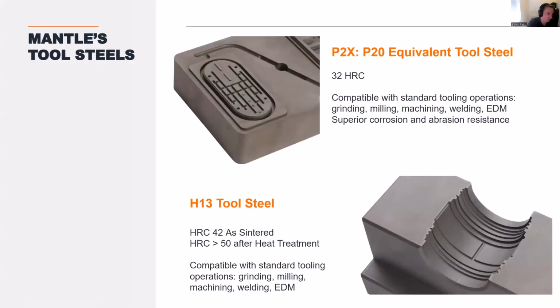Today we have two tool steels available. A P20 material, which we actually call P2X. It's very, very similar to a P20 material. It actually has superior corrosion resistance that comes out of our process with a 32 HRC. And then we have an H13 tool steel, which is actually our more popular material. Comes out of the furnace at a 42 HRC and can be heat treated all the way up into the 50s. Both of these, I should note, are fully compatible with traditional finishing, because we like to say our process gets you anywhere from 50 to 75 to 95% of the way there. Generally, tools need a little bit of grinding or wire EDM for ejector pins and things like that just to touch them up.